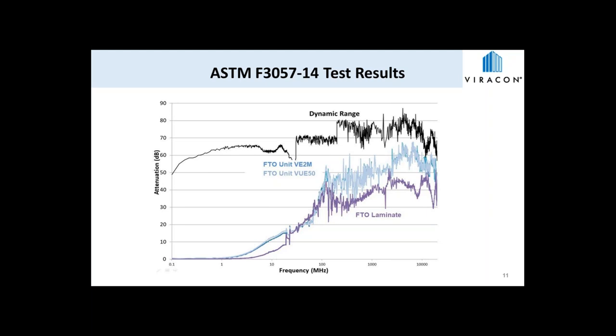However, this time the focus is very glass specific, where every aspect of the method applies, unlike the modifications to the IEEE test. So once again, we have the dynamic range up top, the same colors for the FTO film and FTO units, and the purple for the FTO laminate. Looking at the lower frequency range, below about 1 megahertz, neither the FTO units nor the FTO laminate block much signal at all. Between 1 and 100 megahertz, the electric field, this is where the samples start to block some of the signal. As expected, the FTO laminate lags behind a bit when compared to the FTO units. Looking back to the IEEE test, it's very similar in that aspect.